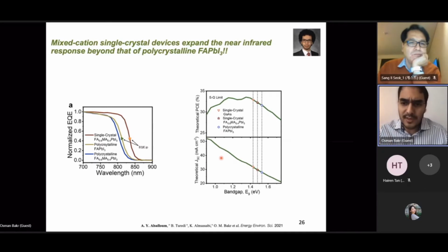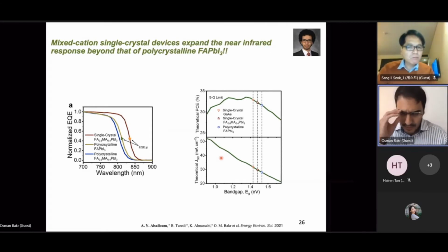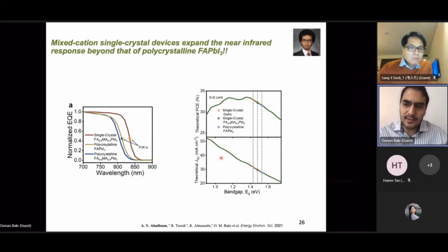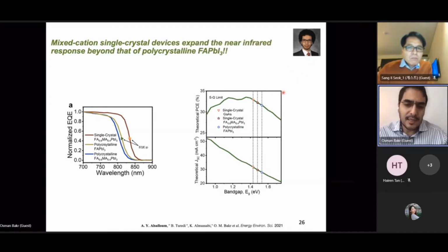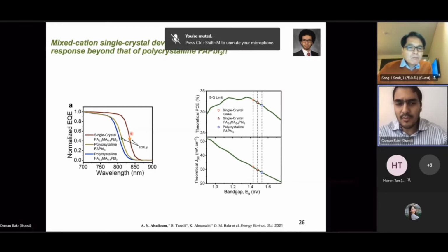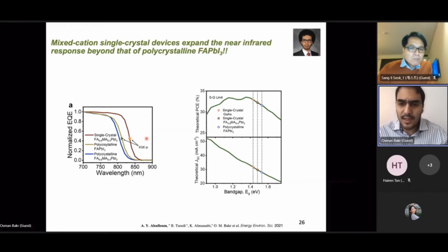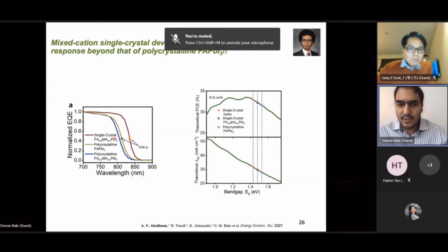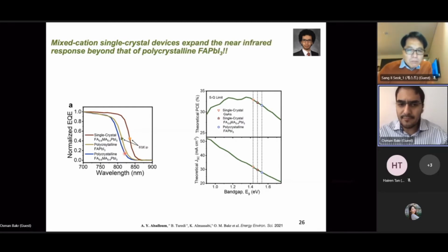The next step was for us to ask, can we play around with the band gap? Can we shift the band gap with the single crystals? And of course, people have done a lot of work on polycrystalline films, but growing single crystal cation mixtures is not that trivial. And with a lot of effort, one of our brilliant students, Abdullah Saloom, found that he could grow mixtures of formamidinium, methylammonium, lead iodide crystals. And what was really surprising is that, in fact, he was able to shift the band gap. He showed that formamidinium 60%, methylammonium 40% had a narrower band gap than polycrystalline formamidinium lead iodide.